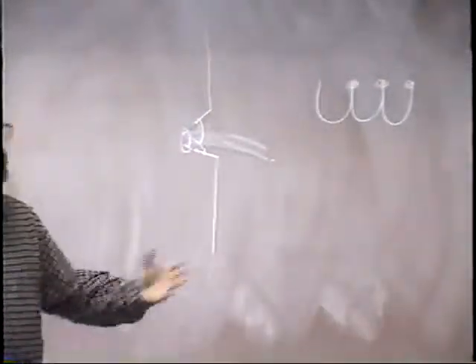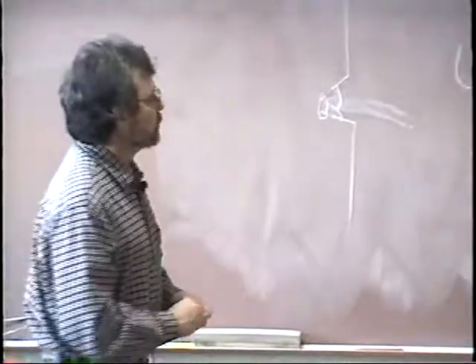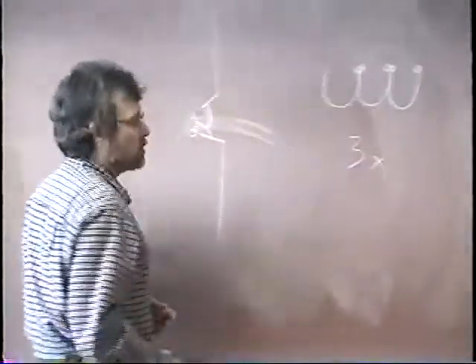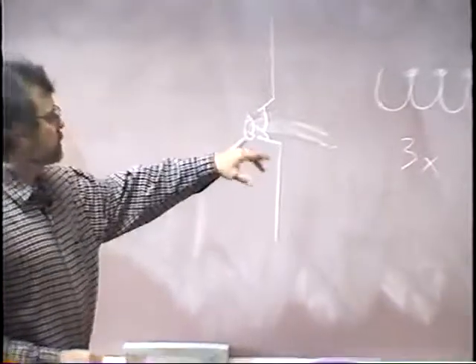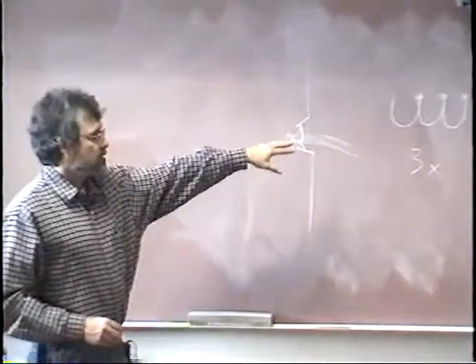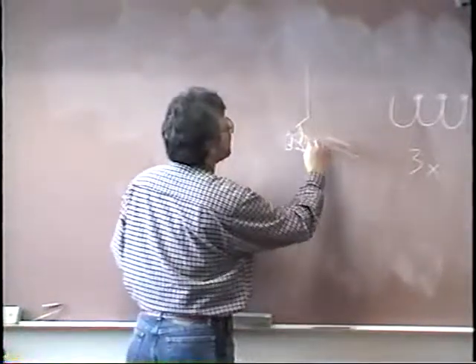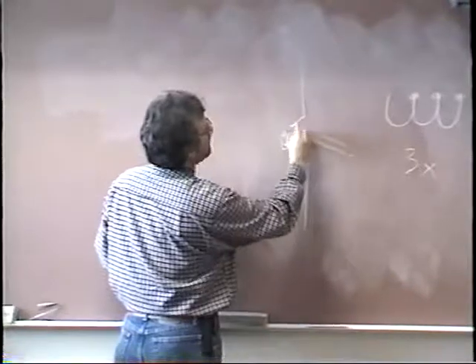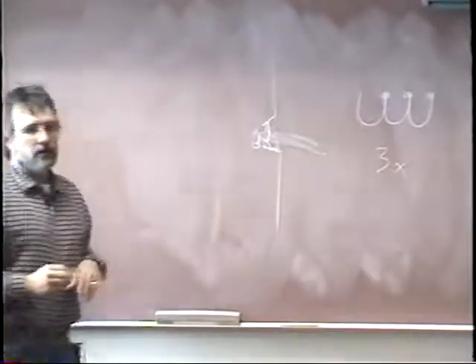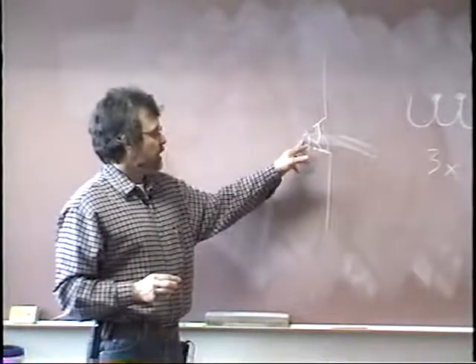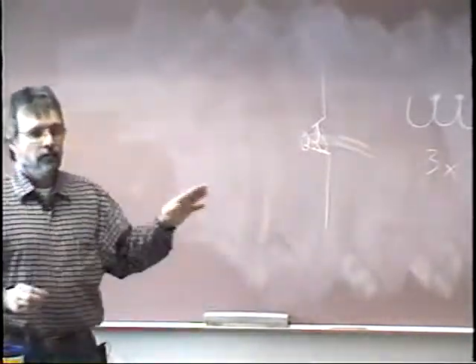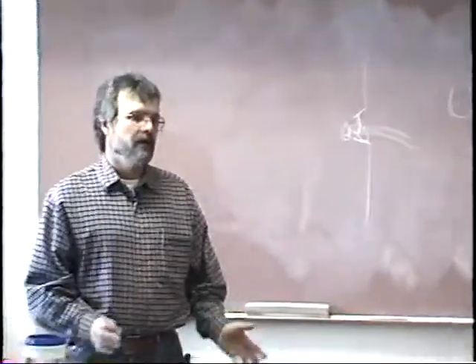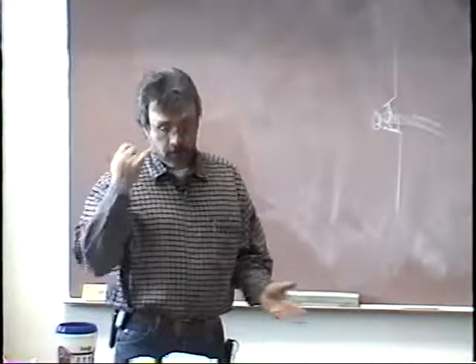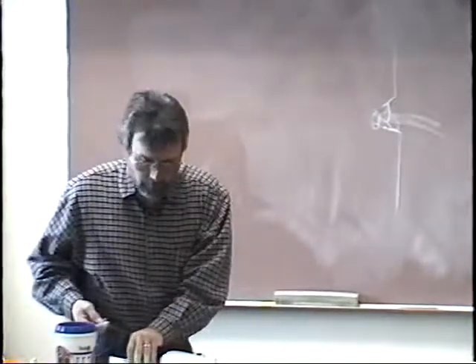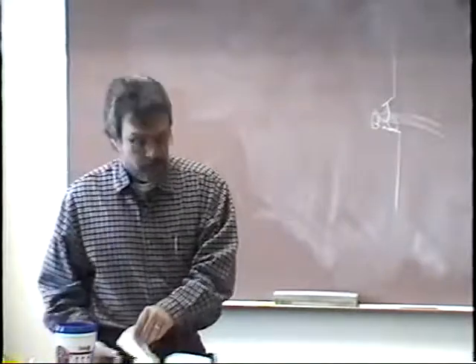So if you're going to use this W technique, and I have seen some people use it to weld things all the way out, don't go any wider than 3 times the electrode when you're doing it in the horizontal position. The problem with this, and the reason I don't like to use this beyond the second pass, is because if you do, it's going to sag on the top, and it's going to sag here, and you're going to get overlap on the bottom of it. So once you've gotten past your root pass and your second pass, go to stringer beads, because you don't have any problem about it sagging or catching undercut or catching overlap if you're using stringer beads. And incidentally, off of page 145, there are 2 questions coming.